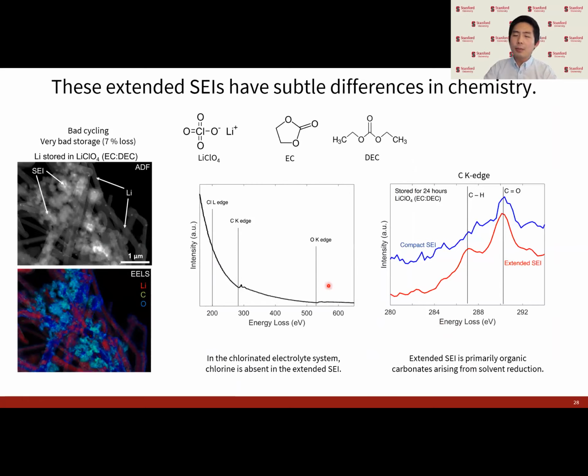Looking closer at the lithium perchlorate system, which shows the worst storage performance, which loses about 7% capacity in 24 hours, we can see that there actually isn't any chlorine signal in the extended SEI shown here. Instead, there's only carbon and oxygen, along with some lithium. From the carbon K edge, this extended SEI is mainly organic carbonates, meaning that this significant extended SEI deposition is coming from the continued reduction and precipitation of the electrolyte solvent.